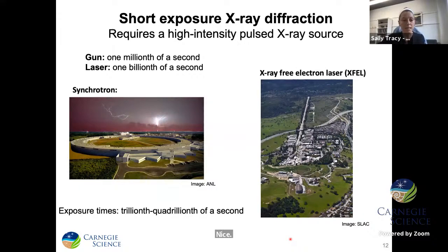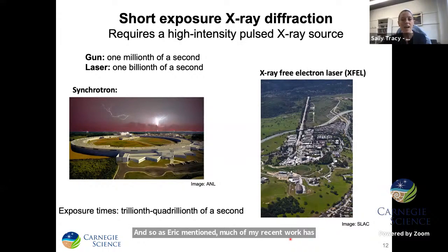And so, as Eric mentioned, much of my recent work has been carried out at high intensity pulsed X-ray sources. Going to these facilities, where we have access to ultra bright high energy X-rays, allows us to effectively take snapshots of a material's crystal structure using very, very fast exposure times, down to a femtosecond or a quadrillionth of a second. And so I'll talk about a few experiments in the coming minutes.